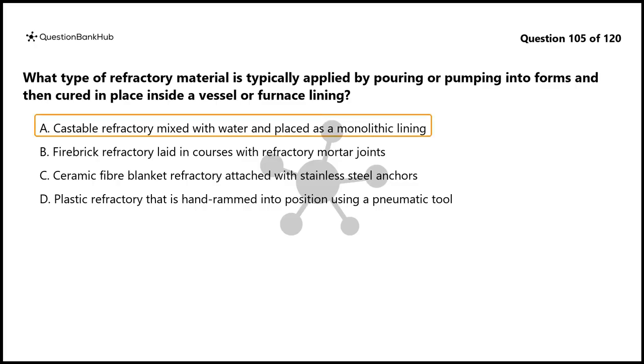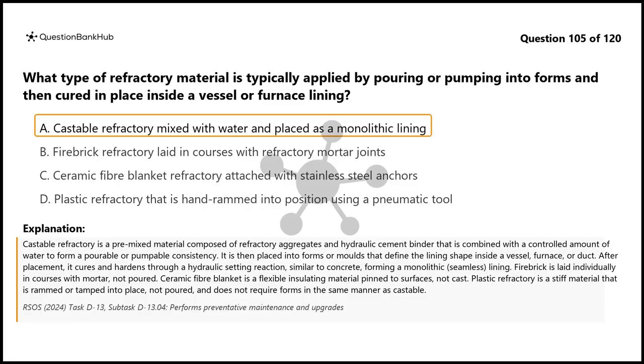The correct answer is A. Castable refractory is a pre-mixed material composed of refractory aggregates and hydraulic cement binder that is combined with a controlled amount of water to form a pourable or pumpable consistency. It is then placed into forms or molds that define the lining shape inside a vessel, furnace, or duct. After placement, it cures and hardens through a hydraulic setting reaction, similar to concrete, forming a monolithic, seamless lining.